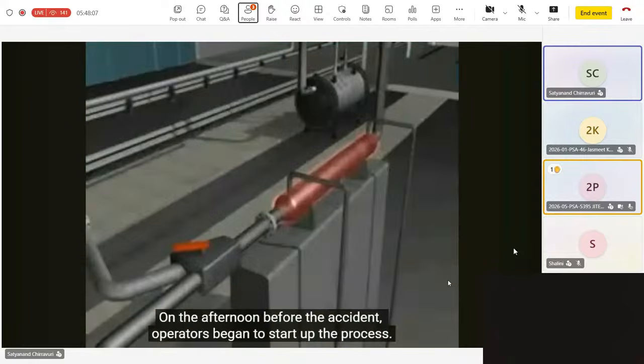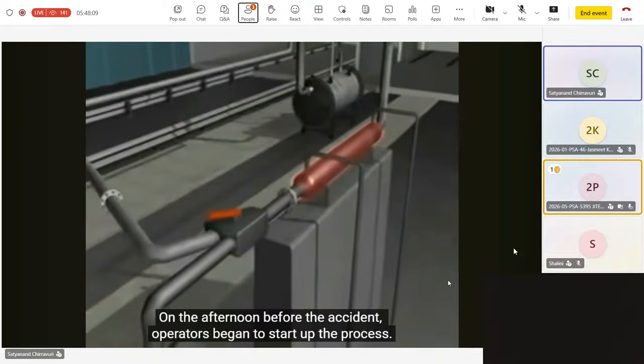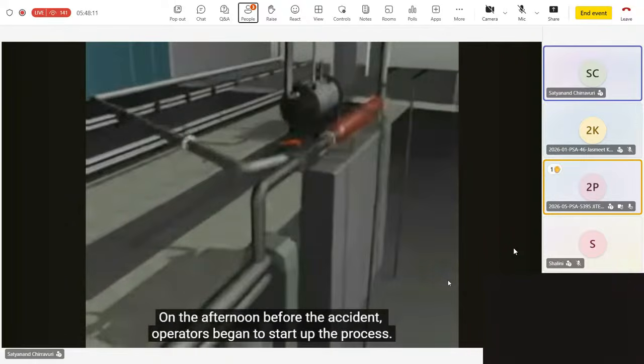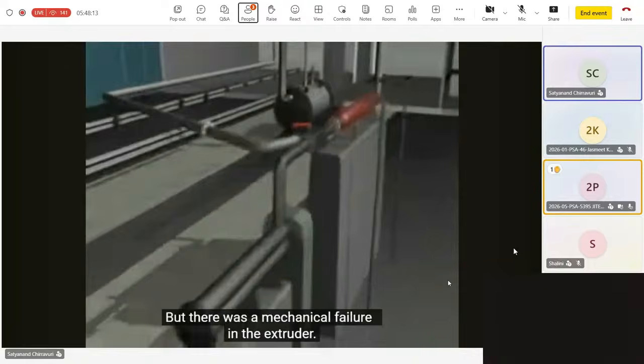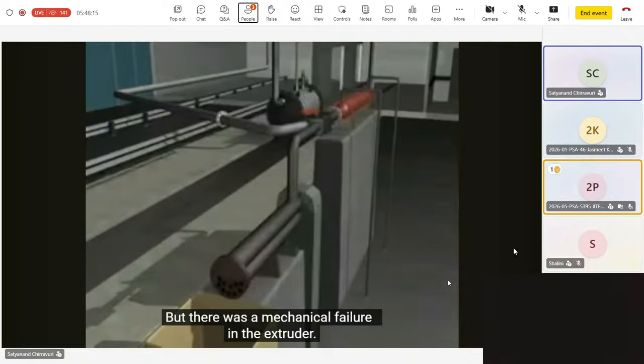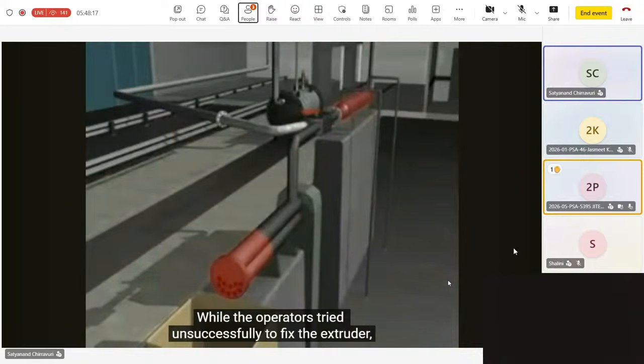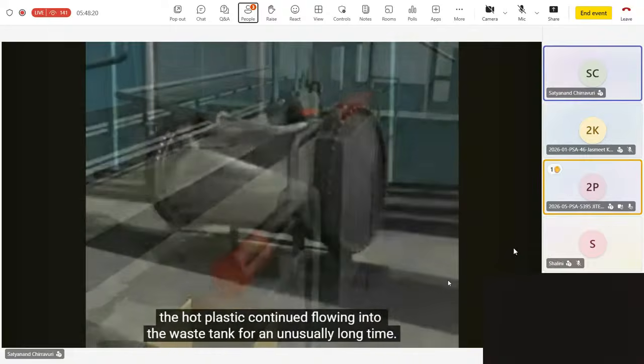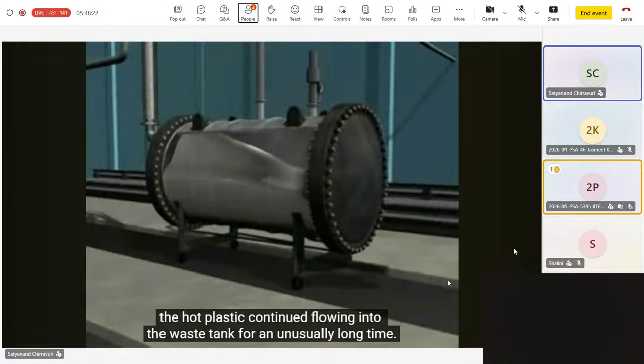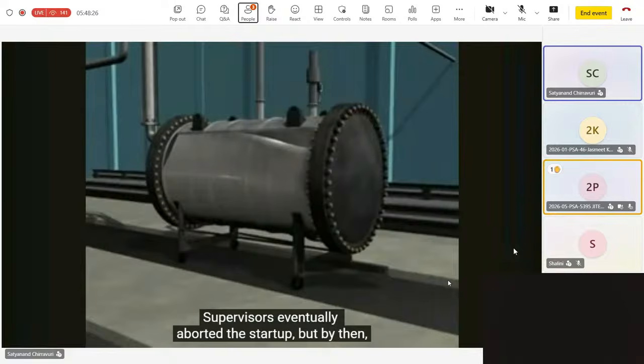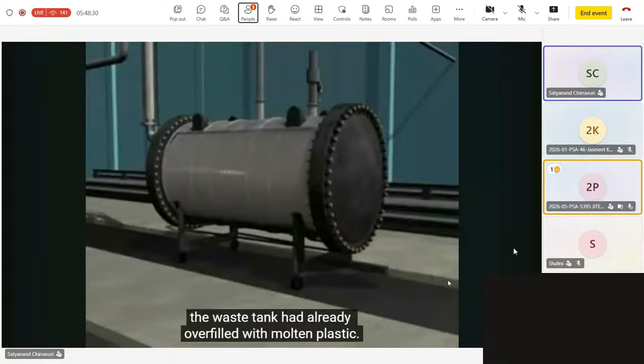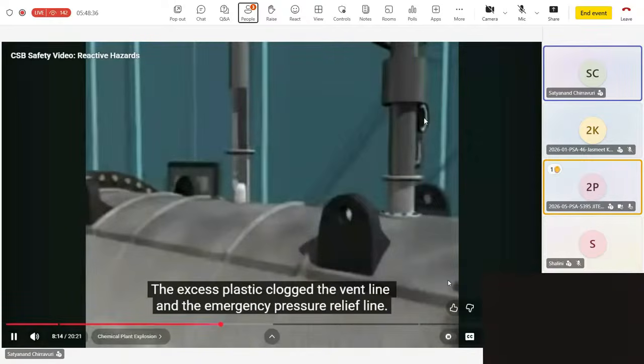On the afternoon before the accident, operators began to start up the process. But there was a mechanical failure in the extruder. While the operators tried unsuccessfully to fix the extruder, the hot plastic continued flowing into the waste tank for an unusually long time. Supervisors eventually aborted the startup, but by then, the waste tank had already overfilled with molten plastic. The excess plastic clogged the vent line and the emergency pressure relief line.